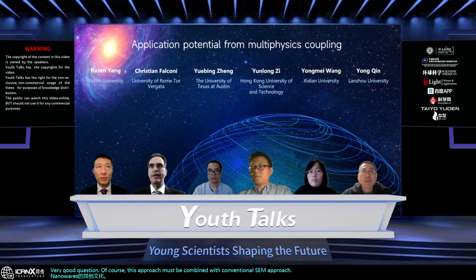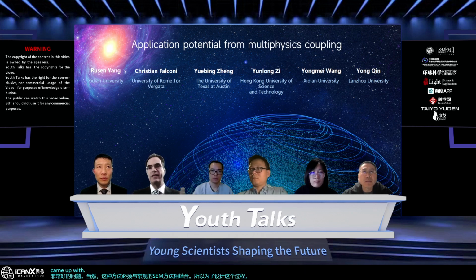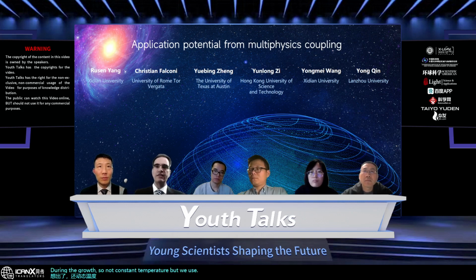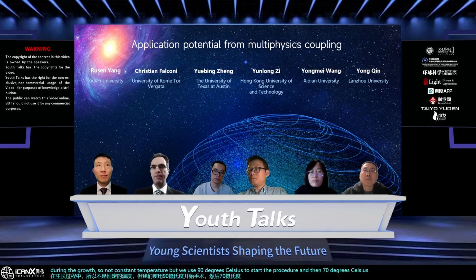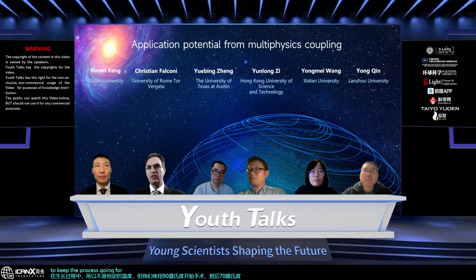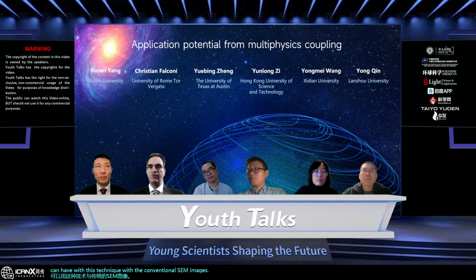So in order to design this process that we came up with, also the dynamic temperature during the growth. So not constant temperature, but we use 90 degrees Celsius to start the procedure and then 70 degrees Celsius to keep the process going for a longer time. So that was the process we designed. But to do that, we combined the information that you can have with this technique with the conventional SEM images. So it's not sufficient for everything.